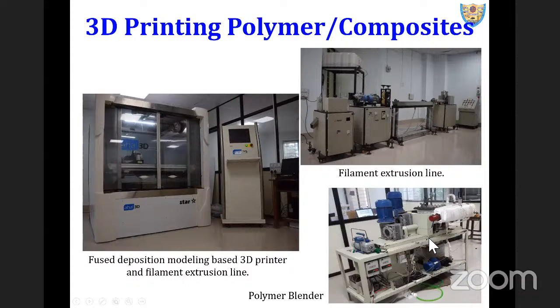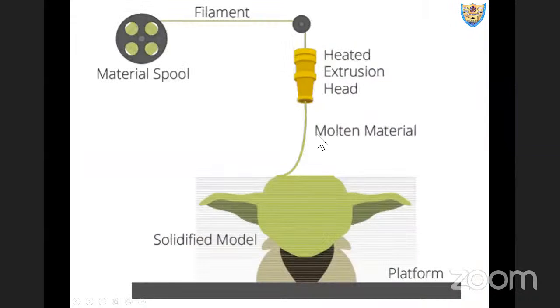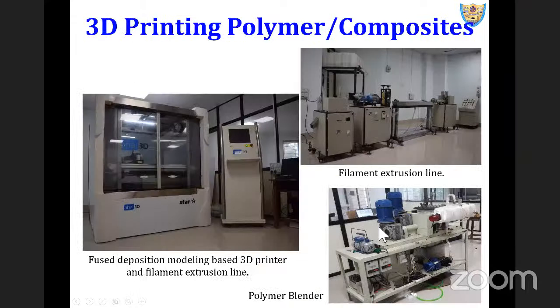The composite blend is prepared in a polymer blender, wherein we mix the polymer and whatever filler you want, melt it, blend it. The blend comes out, we shred it, we chop it, load it into the hopper of an extruder. So this is the first heating cycle. Second heating cycle, and the third heating cycle. The third heating cycle is in this heated extrusion head. So likewise, there are 3 heating cycles the polymer comes across.